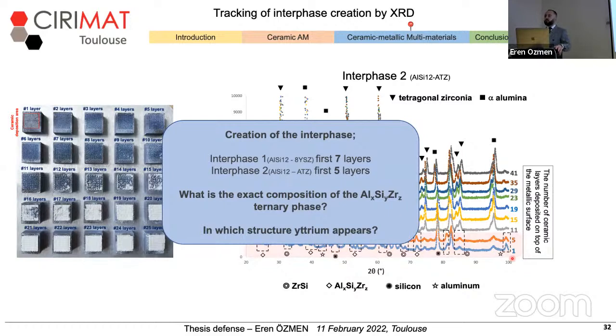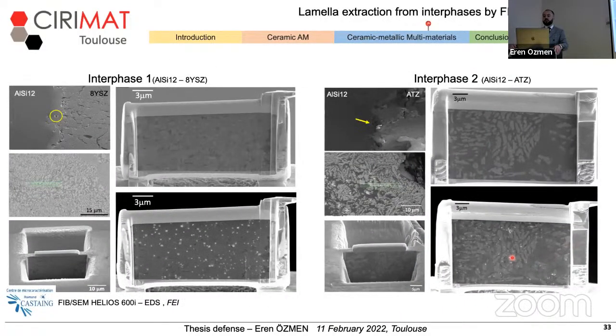However, there are still some questions remaining. For example, what's the exact composition of this ternary phase, which was detected in microdiffraction analysis, and also in which form yttrium appears or disappears from the structure. To answer these questions, I wanted to run a TEM analysis, but for TEM, first I had to extract a lamella from both of my interfaces.